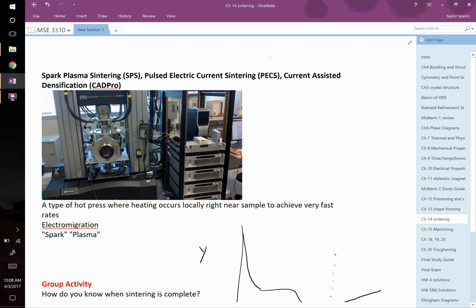And then how do you cool the sample? You actually have water running down through this platen and then back out, up through this platen and then back out. So the punches are actually water cooled themselves. And by doing that, you can cause this thing to cool down pretty quick. And it still is the slowest part of this process. Like I said, sintering takes 5 minutes. Cool down is the slowest part of the whole thing. It takes about an hour, maybe 2 hours.